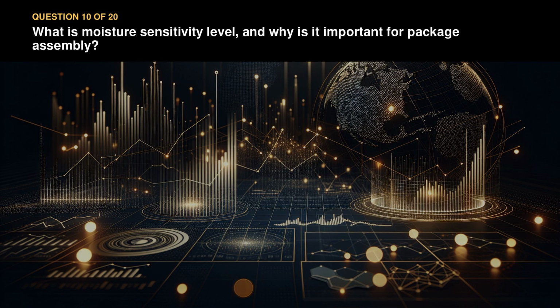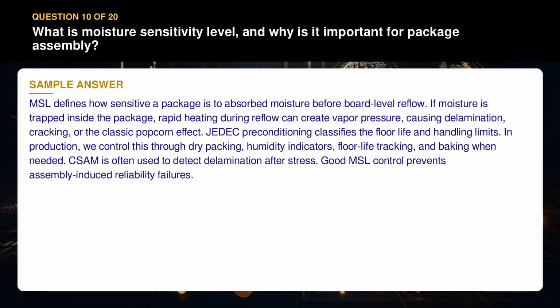Question 10. What is moisture sensitivity level, and why is it important for package assembly? MSL defines how sensitive a package is to absorbed moisture before board-level reflow. If moisture is trapped inside the package, rapid heating during reflow can create vapor pressure, causing delamination, cracking, or the classic popcorn effect. JEDEC preconditioning classifies the floor life and handling limits. In production, we control this through dry packing, humidity indicators, floor life tracking, and baking when needed.